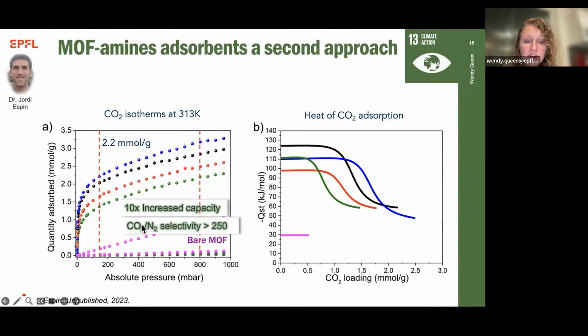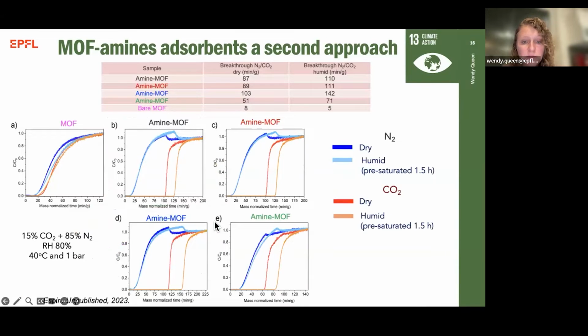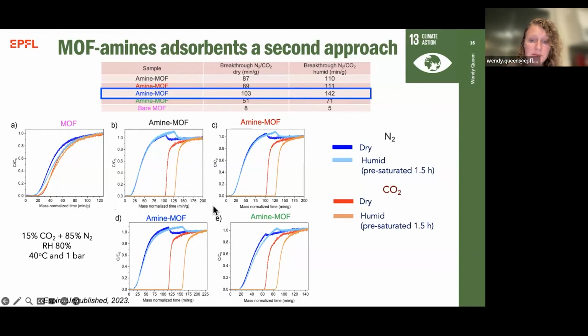And then if we look at the CO2 selectivities of these materials, we again get extremely high CO2 selectivities, which are well above 200 in this case. And so from there, I don't want to go through all of these, but I'll just show you the best performing material. In this case, you can see that we've now been able to improve the breakthrough time from the previous best, which was 90 minutes, up to about 142 minutes under humid conditions, which is really nice.